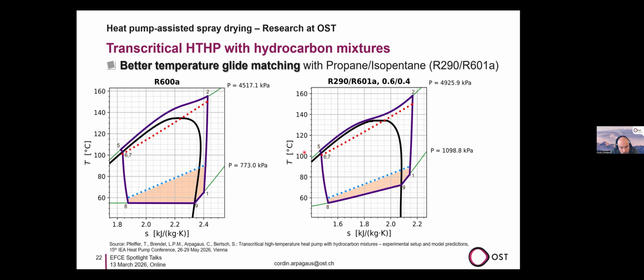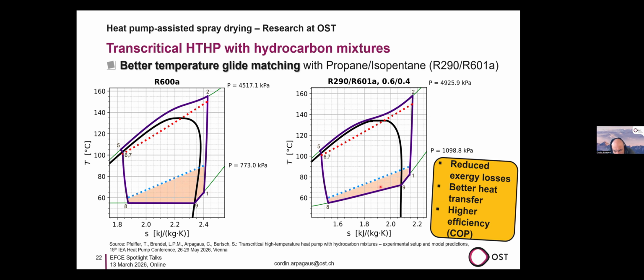And the goal is now to use propane and isopentane, a mixture of 60% to 40%. And here the graph shows the situation. So you see the area on the source side gets smaller compared to here. And what does it mean? So we can reduce exergy losses, the heat transfer gets better, and overall the heat pump COP, the efficiency, can be increased by this additional parameter of using a mixture of hydrocarbons. And that's the main motivation, to match the temperature glides better on the source and sink side.